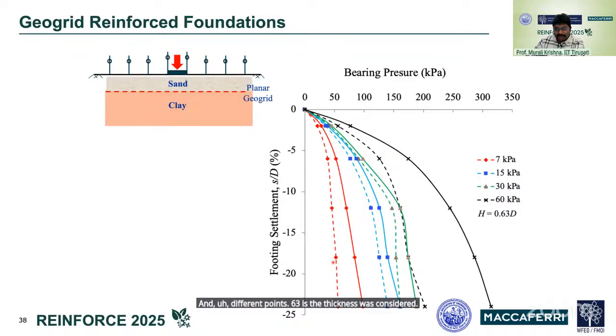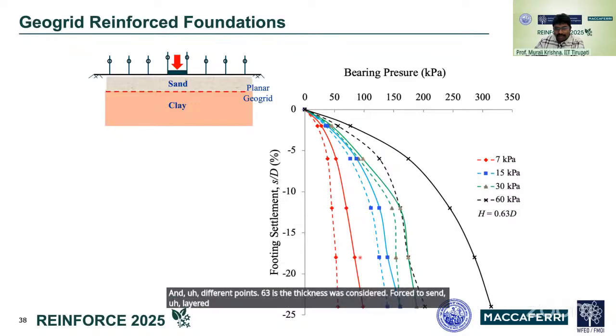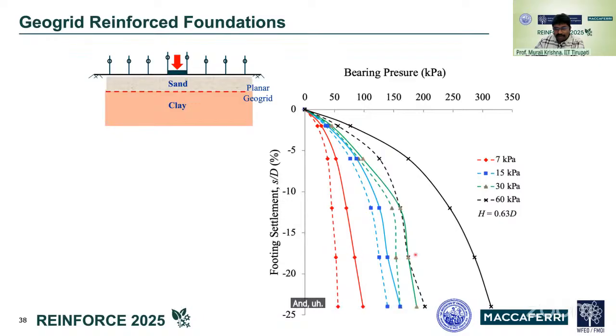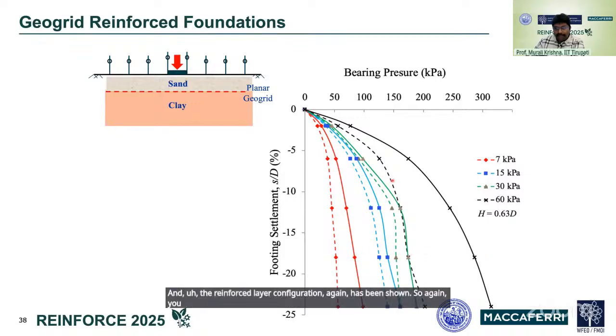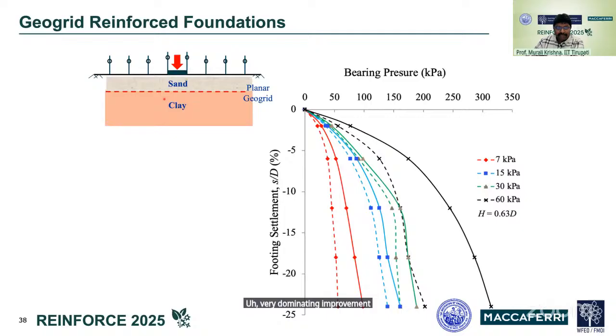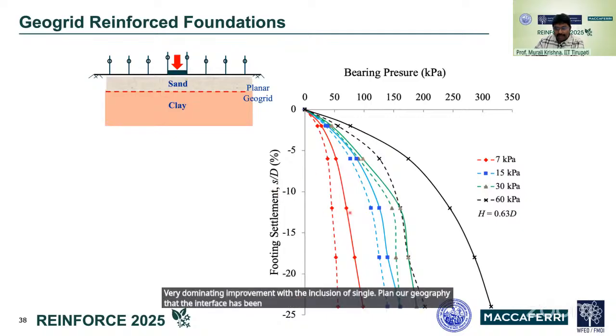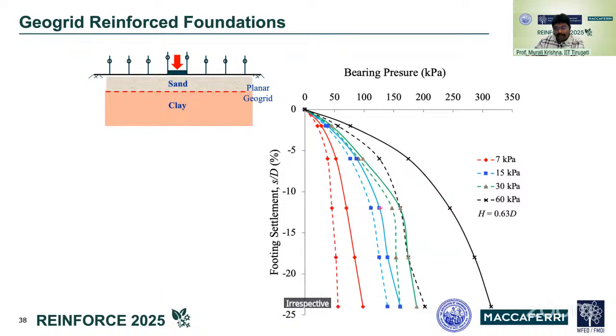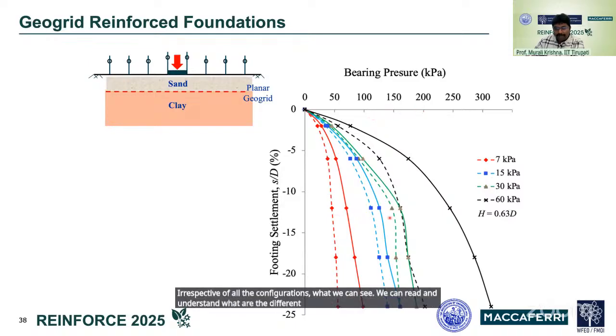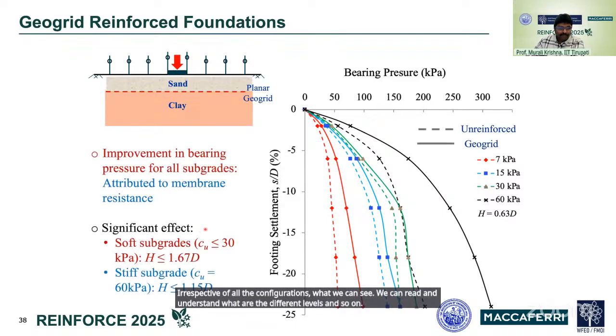Reinforced sand layered configuration, and the reinforced layer configuration again has been shown. So again, you see from the unreinforced case to the reinforced case, there is a significant, very dominating improvement with the inclusion of a single planar geogrid at the interface, irrespective of all the configurations. We can read and understand the different levels and so on.